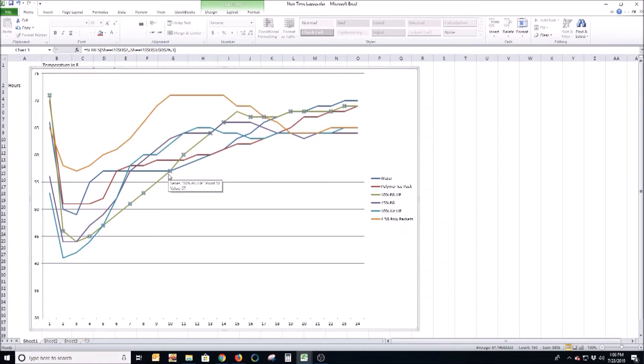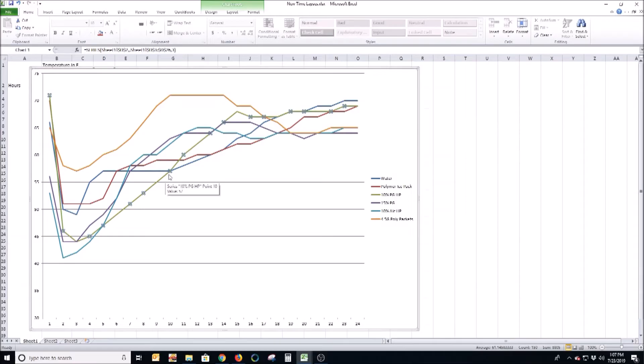And the 10% PG or propylene glycol mixed in with hydrophilic polymer really did the best. I mean you would get 10 hours of cold. So I'll be mixing up some ice packs of this, put more in the cooler than I was using (which was only 500 milliliters of any of these substances that was frozen) and see how well it does, how cold it actually gets that little cooler and how long it lasts. So let me go ahead and make up a few of these ice packs and I'll show you exactly how I'm doing these.